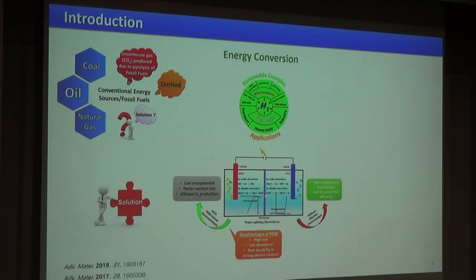But both these processes are associated with high overpotential, because water is a quite stable molecule and it doesn't split at its thermodynamic potential of 1.23 V. So we need excess energy, which is identified as the overpotential. To reduce this overpotential, we need suitable electrocatalysts which can catalyze these reactions and speed up their kinetics. Generally, platinum group based materials are regarded as the commercial or benchmark catalyst, but their high cost and low abundance limit their application in the long term and also for large scale production.